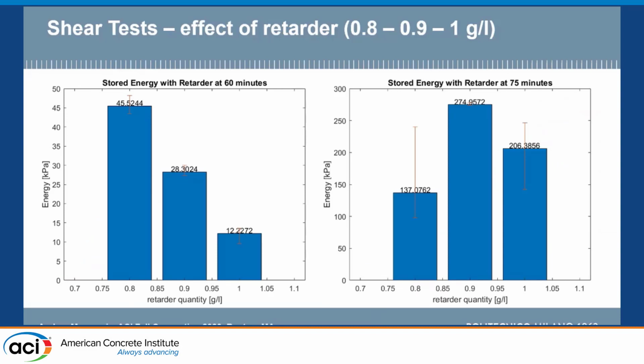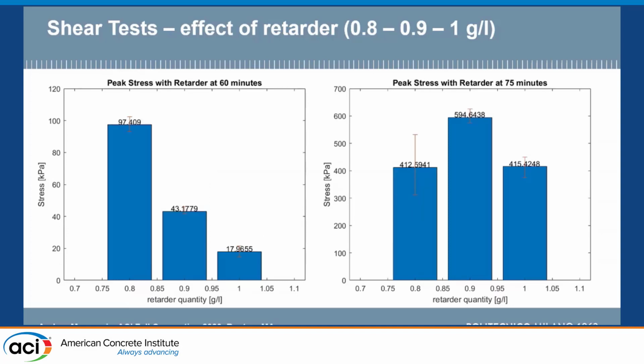And here you can better see from the stored energy for different quantities of the retarder, there is a clear linear dependency of the energy on the quantity of the retarder at 60 minutes, whereas at 75 minutes there is no clear evidence of this dependency. So we can say that it's too late for the shear strength to have any effect of the retarder quantity. And again, looking at the peak stress, there is an almost linear trend of the peak stress with the retarder quantity at 60 minutes, and no longer the effect at 75 minutes.